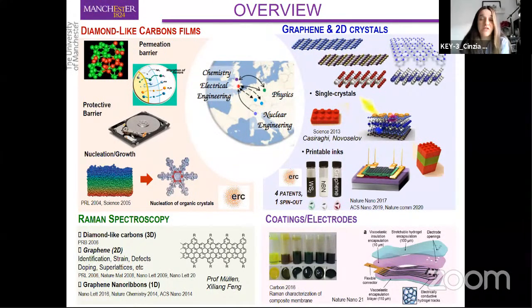Therefore, I developed a strong expertise with this technique that I then applied to other carbon nanostructures: nanodiamond, diamond-like carbons, carbon nanotubes, and of course, graphene and graphene-related materials. We published several contributions where we demonstrated how powerful this technique is for the characterization of graphene and related materials. Today I'm still doing Raman spectroscopy, although not as the main activity of my research group. We are applying Raman spectroscopy to quasi-one-dimensional aromatic structures, meaning graphene nanoribbons produced by bottom-up approaches in the labs of Professor Klaus Mullen and Professor Xinliang Feng in Dresden. We are also applying Raman spectroscopy to study nucleation and growth of organic crystals, which is a new project I may touch upon towards the end of my talk if there is still time.